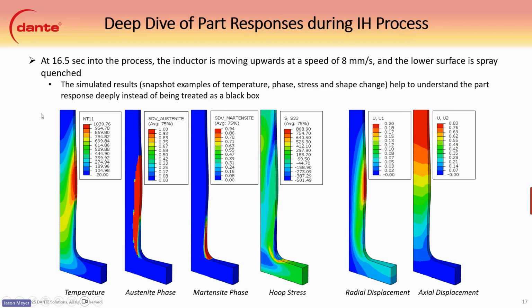So what's nice about modeling is we can do a deep dive into the part response. So basically, we don't just see the black box. You put the part in, you get the part out, and that's what you get. So we're able to step through and see critical regions. One of them that we noticed was at 16.5 seconds. The inductor is moving up at its constant rate of 8 millimeters per second, and the lower area is actually being spray quenched. So these are just results at that 16.5 second time during quenching.